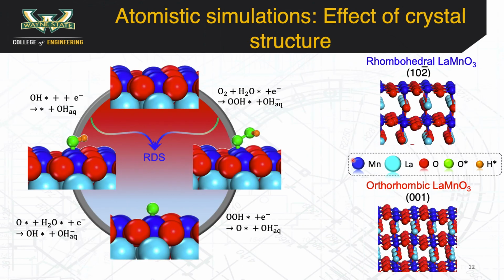We then benchmark our experimental observations with theoretical calculations. A (1,0,-2) manganese oxide terminated surface is used to model ORR on rhombohedral LaMnO3, while a (0,0,1) manganese oxide terminated surface is used to model the orthorhombic structure. A 4-electron ORR mechanism is modeled where O2 is initially protonated to form a surface adsorbed OOH. The O-O bond in OOH is then cleaved to form a surface adsorbed O. The surface adsorbed O is then protonated, leading to the formation of a surface adsorbed OH. The last step involves the desorption of this adsorbed OH, leading to the generation of a clean site.